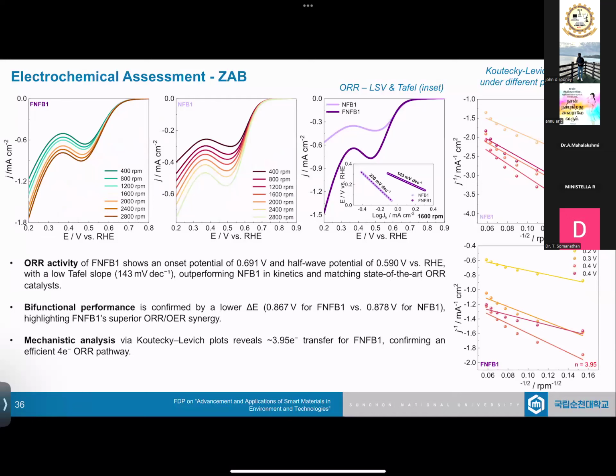Now, moving into ZAB, I'm just going to do it in 2 minutes. So we evaluated the ZAB. We did the ORR studies using the RDE and RRDE apparatus, the rotating disc electrode and rotating ring-disc electrode setup. And we evaluated the material. Again, to be frank, it was not that great. It is not at the level of platinum and carbon, but still the material was able to work in that system. That is very important.